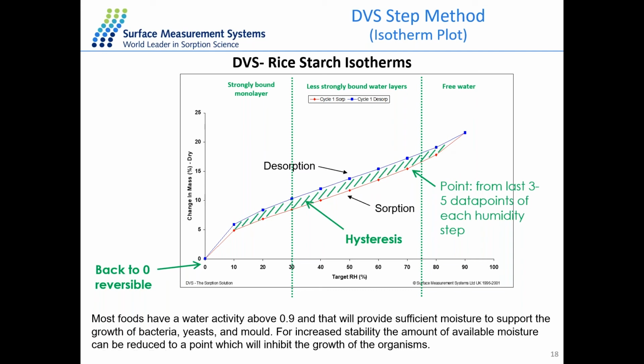Some information we can get from this water isotherm, for example, at 90% RH, this sample can pick up about 20% change in the mass. That means this sample has very good affinity with water. So the water capacity for the sample is about 20%.